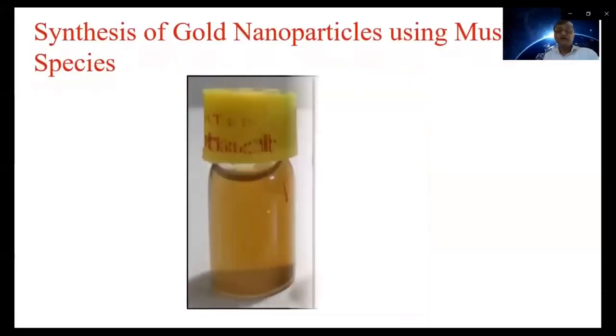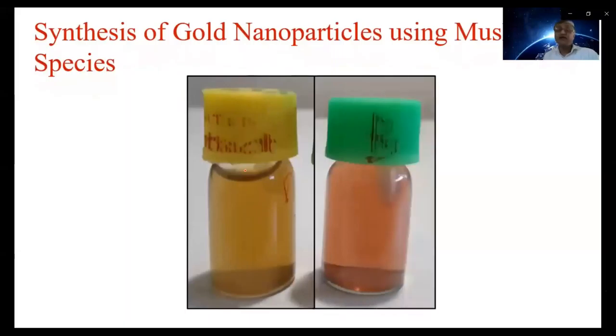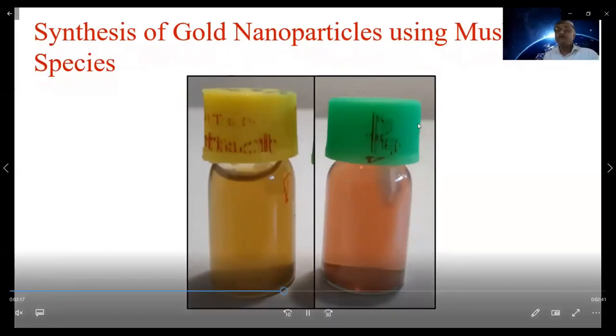Now, how have we synthesized the gold nanoparticles? Here, we have prepared the mushroom filtrate, and that mushroom filtrate is challenged with the gold chloride solution, in equal proportion. And we have seen that the color changes from light yellow to reddish within 12 hours, and that indicates the synthesis of gold nanoparticles.